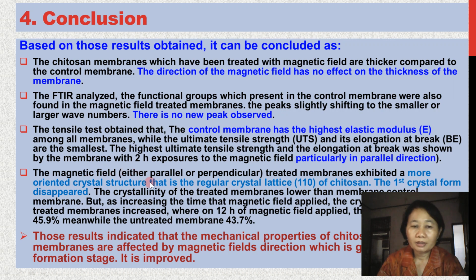The magnetic field, either parallel or perpendicular treated membrane, exhibits a more oriented crystal structure, that is the regular crystal lattice 110 of Chitosan. The first crystal form disappears. The crystallinity of the treated membranes is lower than the control membrane. But as the time the magnetic field is applied increases, the crystallinity of the treated membrane increases, where at 12 hours of magnetic field the crystallinity of the treated membrane is 45.9%, meanwhile the untreated or control membrane is 43.7%.